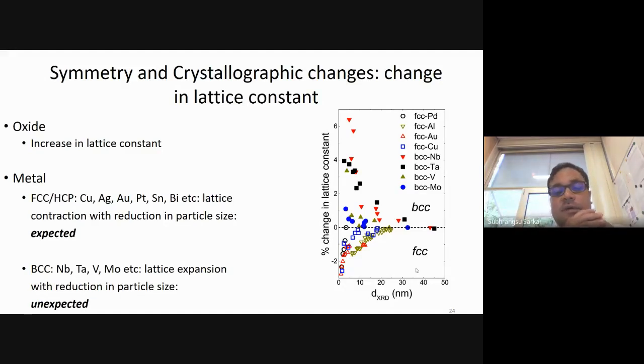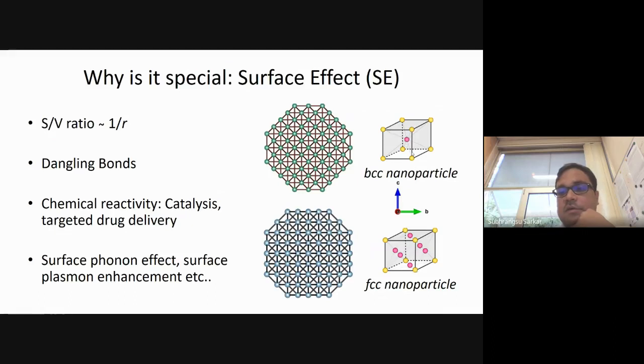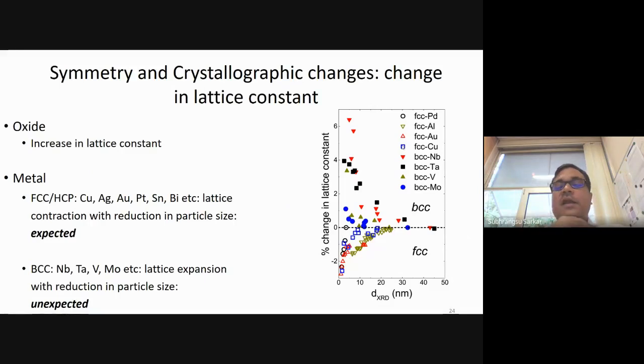However, recently in our lab, we have discovered that if you have a body-centered cubic coordination, like the one described here in the top right diagram, the metallic nanoparticles actually expand in size. In earlier days, people explained this reduction in particle size in metal nanoclusters by the argument that they want to reduce the surface energy. If they reduce the surface area, they are technically reducing the surface energy, and contraction would be preferred. But it doesn't explain the observation that we recently had in BCC systems, which is much more complex. If you look at the graph on the right, the amount of expansion in a BCC cluster is much more than in an FCC cluster. However, it still remains an open question as to why this happens.